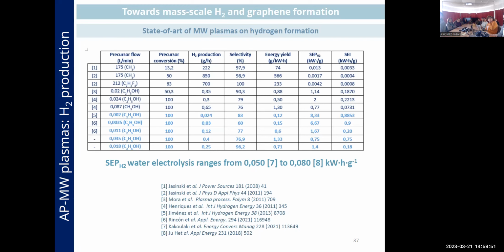If we compare with the use of microwave plasmas for the production of hydrogen, we can have a look at the energy which is required for hydrogen production in water electrolysis, which is the most common technology for the production of hydrogen, and it ranges between these two values. Have a look at our values here. You can see that they are much higher, two orders of magnitude. So we are still far from having a competitive technology to produce hydrogen. But once again, keep in mind that this result was obtained with the torch, which can be prepared to multiply the values of hydrogen. So we are working in that way.